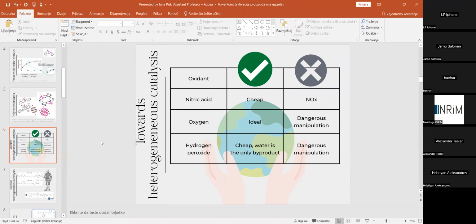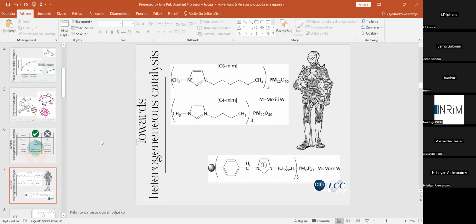During the reaction, some of them were more soluble, some of them less soluble. And in order to get a catalyst that could be recycled and reused, we started to think about heterogeneous catalysis. When we thought about the protocols we could apply, we wanted to stay in the area of green chemistry, meaning we wanted to use oxidants that were less harmful and more ecologically appropriate. For that reason, we decided to use hydrogen peroxide, because it's quite a cheap oxidant, and the only byproduct of the reaction is water, which could be quite easily purified at the end of the reaction.